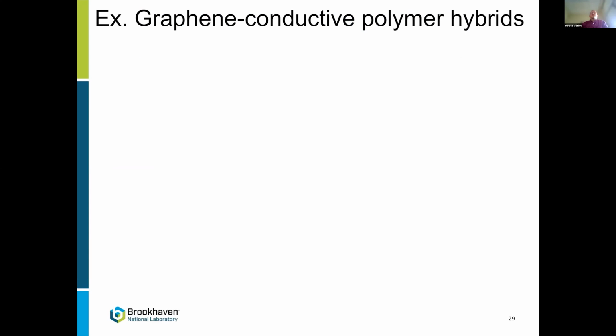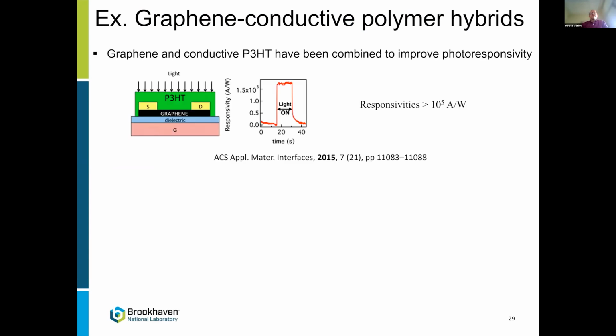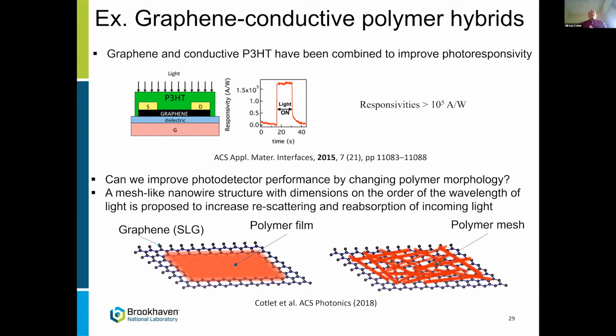The final example that I'm going to show today is graphene conductive polymer hybrids. Graphene, like I said, has high conductivity, but I think the absorptivity of this material is somewhere like 2%, and this has to do with being a semi-metallic, bandgapless nanomaterial. One can add the conductive polymer, which is a stronger absorber, on top to improve the responsivity of this material. So we can drop cast or spin cast a very thin polymer film on top of graphene, make a device and measure the responsivity. But how about if we can further improve the detector performance by changing the polymer morphology?